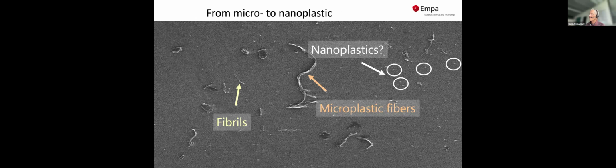And we also investigated this, for example, looking at the concentration of nanoplastics by one measuring technique, the nanoparticle tracking analysis. And you see here with repeated washings, we find for a range of different textiles initially a lot of these nanoparticles released. And then it levels off. And after some time, you cannot extract any more nanoplastics. And looking at the surface of the fiber, it seems they come from production. There's something on the surface. And after washing, the surface is more clean.